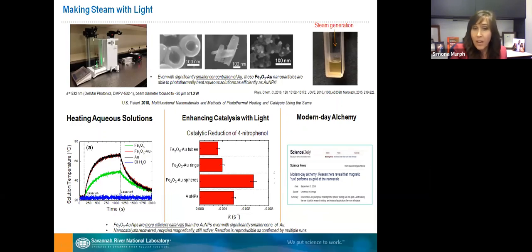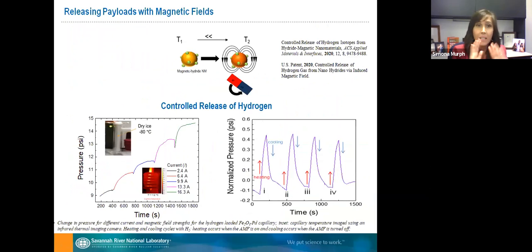The benefit of this, of course, is that you also have the magnetic functionality, and you can couple that. The last application that I want to mention briefly here is that when you have this magnetic functionality, we can also heat the nanoparticles and the environment by using a magnetic field. So what we did here, we coupled the magnetic nanoparticles with some palladium. Palladium is a very great material for hydrogen absorption, and you can control the absorption and desorption behavior of the hydrogen. Just imagine the hydrogen economy, hydrogen cars. How much hydrogen can you release at one time without having a huge release of hydrogen?